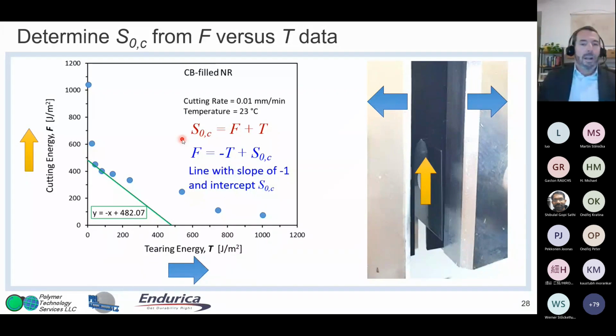And I've taught classes where I go over this method, and it involves plotting F versus T, and then you have to use a line with slope of -1, right? Basically just rearrange this equation. And that allows you to find out when you fit through these lowest data points, get this S0C. But I saw a lot of puzzled looks every time I taught this.